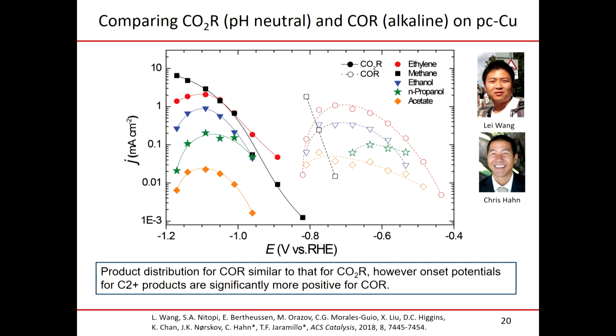Lei and Chris wanted to look at this chemistry. CO2 electrochemistry, I already showed you what Kendra and Natasha had done. They wanted to see what happens if you take that same copper and do CO reduction in alkaline versus CO2 reduction in pH neutral. When you do CO reduction, you don't form an equilibrium with the water, so you can choose whatever pH you want. And for the reasons that Mark brought up earlier, there's a lot of advantages to going alkaline, and this is shown here. You basically make the same usual suspects of products.